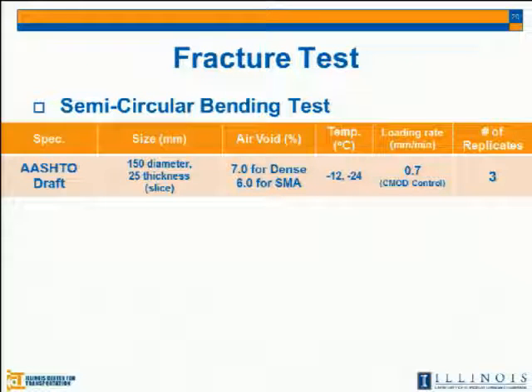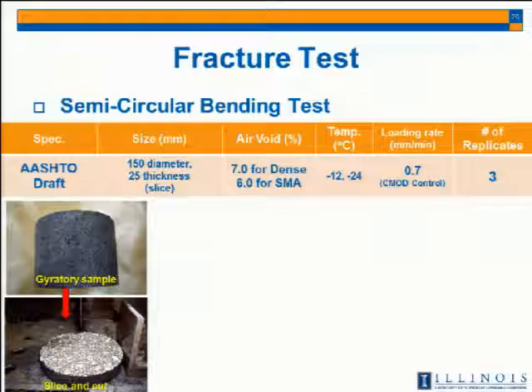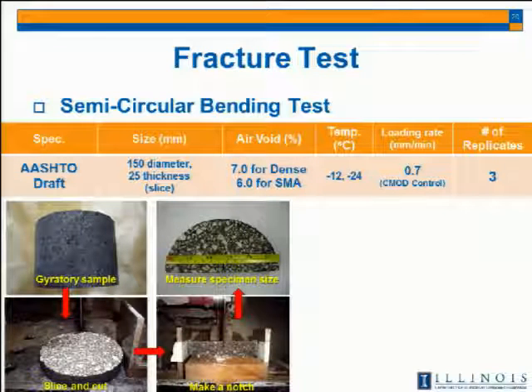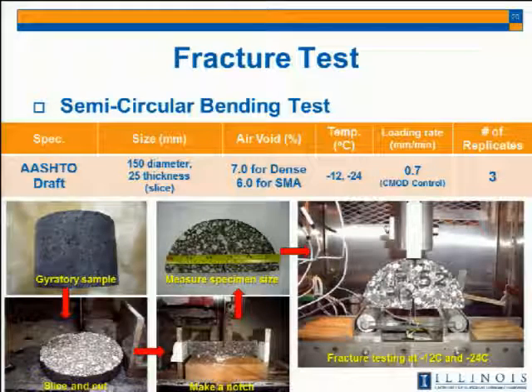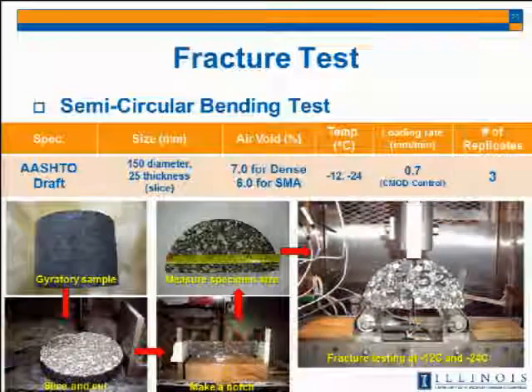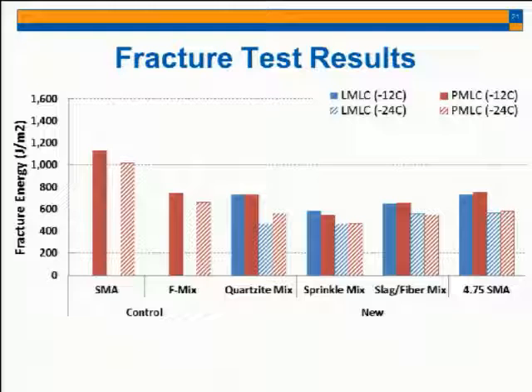The other one is the fracture test. We use the semicircular bending test. After we make a gyratory sample, we slice it and then cut it in half and then make a notch, and then measure the ligament area to calculate the fracture energy. We did this test at 2 temperatures, which are -12 and -24.